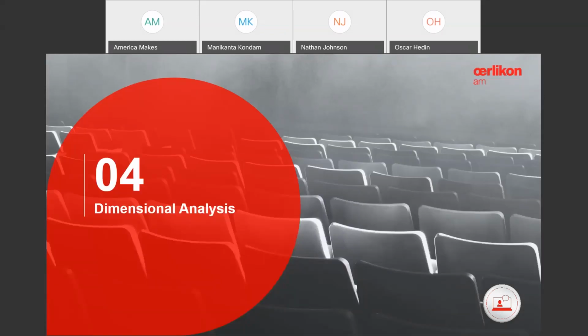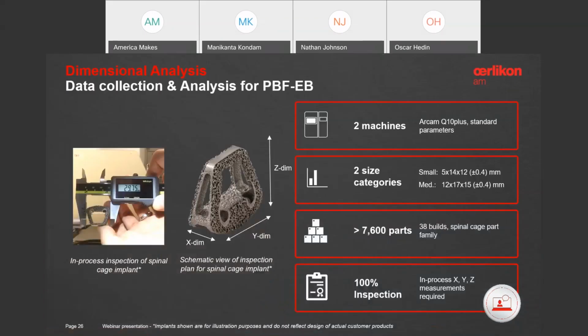We're now going to switch gears a little bit and move over to the dimensional data analysis. Our in-process inspection plan for this implant calls out a number of dimensions, including overall height, width, and depth. Since the measurements are taken as printed, we've implemented pretty generous tolerances, plus minus 0.4 mm in all directions. The implants are grouped into two categories, small and medium, based on their footprint size, with the overall dimensions ranging from 5 by 14 by 12 mm for the smallest footprints, up to 12 by 17 by 15 mm for the largest.